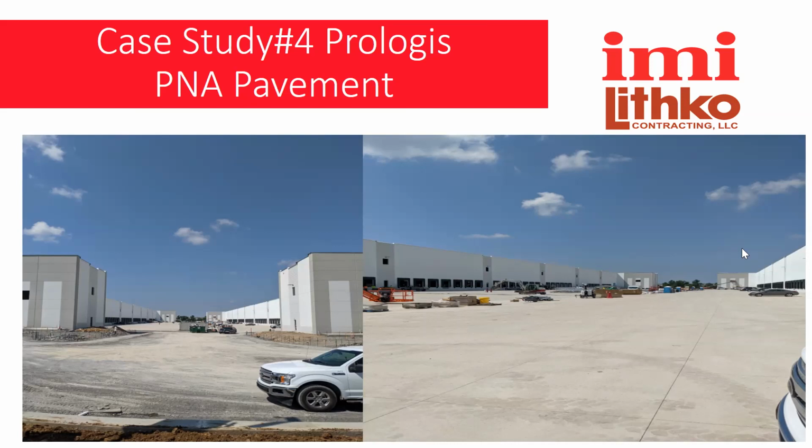On top of all of that, we did have to use 4 pounds per yard of macro fibers. So different challenges hit us, but we were able to reduce our total cement content by around 3 to 5% total. So we were able to meet all these requirements as well as lower that carbon footprint.